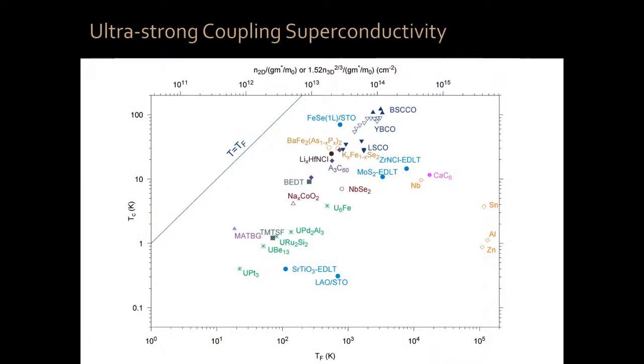It is an even more interesting superconductor than the bilayer itself, much more tunable and more strongly coupled. In particular, one of the things which is interesting with both the bilayer and the tri-layer case is the following. When you discover a new superconductor, you can wonder, okay, how strong is the superconductor? And one way of characterizing that is by saying, what is the value of the absolute critical temperature? That's okay. It's important for applications, but it's not the one that gives you more physics information about how strong the superconductivity is. What typically we do is we create a log-log plot of the critical temperature of the superconductor versus the Fermi temperature or density of electrons in the system, okay?